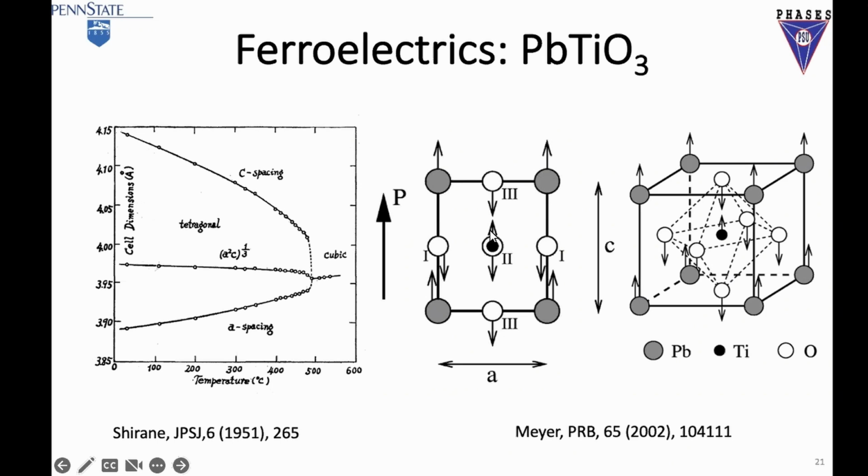Because of those observations, you of course know the famous Landau theory, and they use this fitting. You get a curve where the polarization goes to zero at a high temperature. Above this point, macroscopically the polarization becomes zero. So Landau theory explains this, where you fit the coefficients that people are using today. Those coefficients were originally developed at Penn State by Professor Eric Cross and his team in the 1970s.